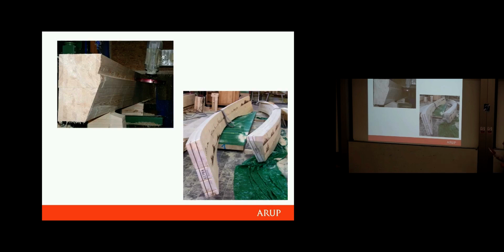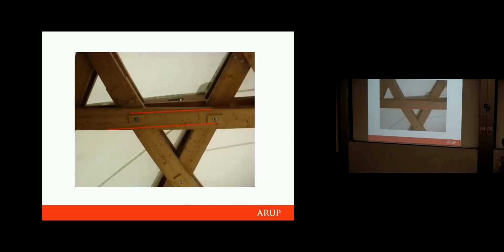So we could really only do that where the members were relatively straight up in the body of the roof. What we did was we said we can only do that where the slope of the fibres is going to be up to about 1 in 10. And where the slope was going to be more than that, we couldn't do this. We had to go for proper two-way lamination. So there you can sort of see the finished roof.